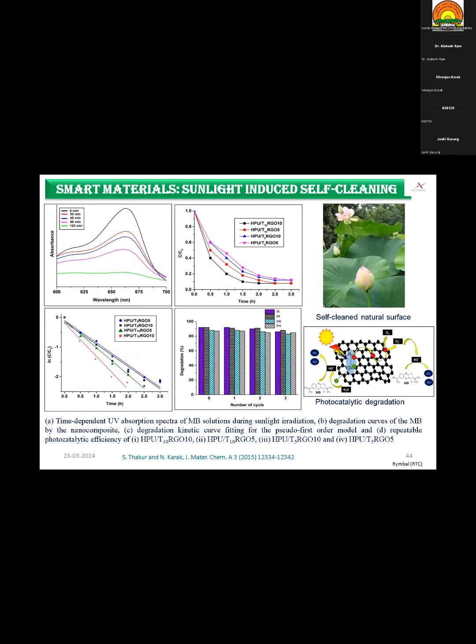This lotus effect is obtained from the photocatalytic effect, which results in the formation of superoxide and hydroxide radicals by absorbing sunlight, through excitation of electrons in the reduced graphene oxide or reduced carbon dot system. Those oxide or superoxide species are so reactive that they can oxidize the dye molecule or detergent and degrade it into carbon dioxide and water, and the surface becomes clean.